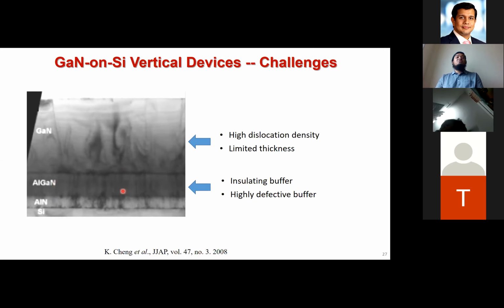This turns out to be very defective, and as we can see, some of these defects are visible in this TEM. If we try to grow a thick GaN layer, say more than 5 micron, this gallium nitride starts to crack and show defects, which is not good when we are trying to make a power device which transports current in a vertical direction. It has been a major challenge over the last decade or so to commercialize these power devices on gallium nitride.